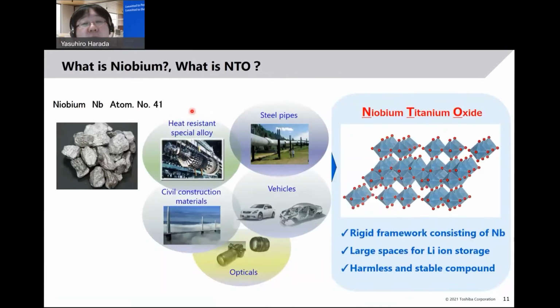As you know, niobium is a metallic element with the symbol of Nb and the atomic number of 41. This niobium is widely used for not only metal products like this, but also optical products. The anode material, niobium titanium oxide, is a kind of ceramics with a rigid framework consisting of niobium and titanium. This material has a large space for lithium-ion storage and thermal stability up to 1000 degrees Celsius.